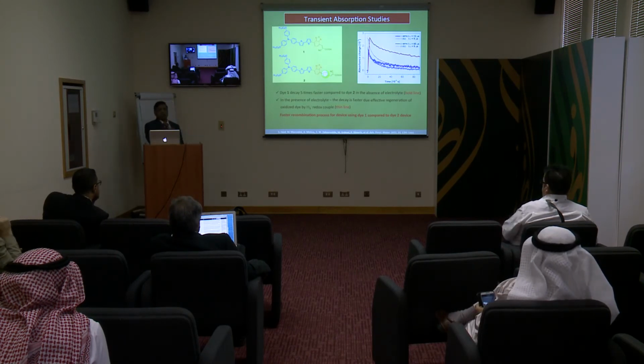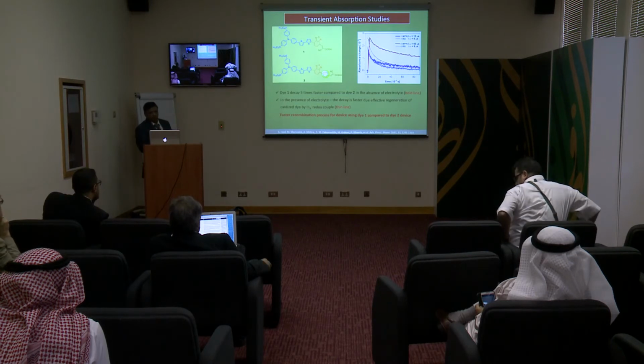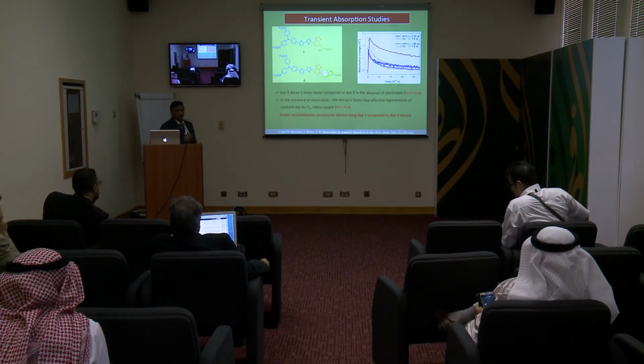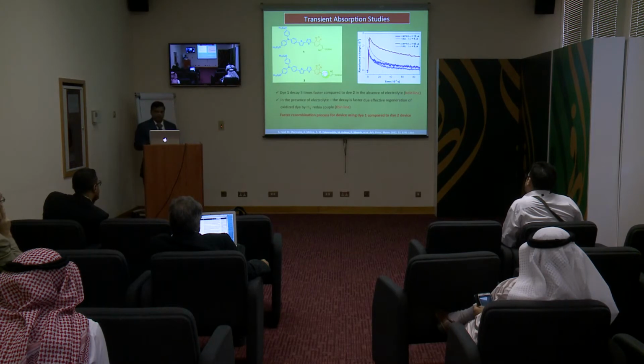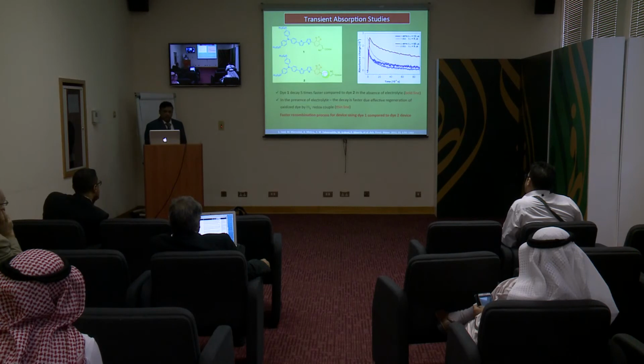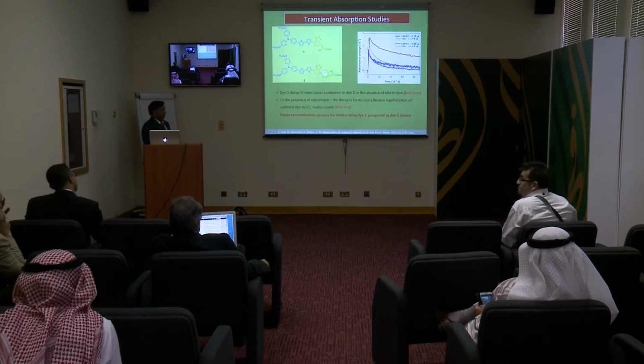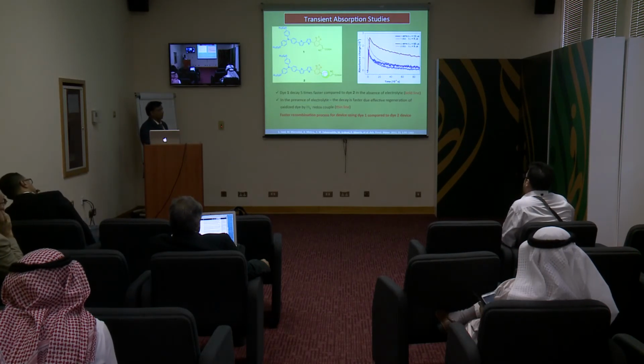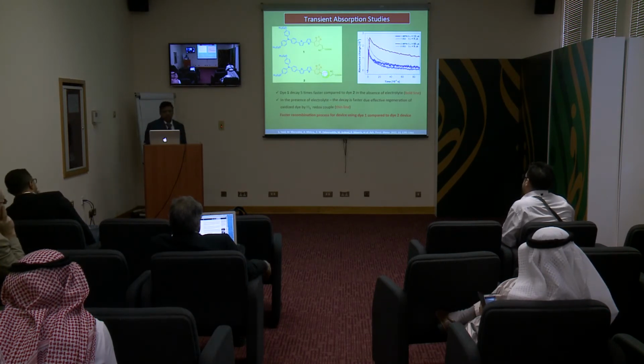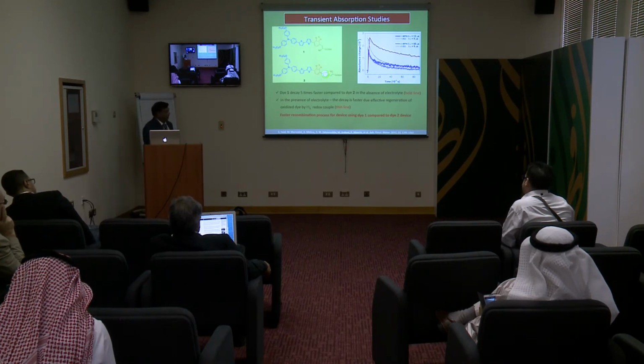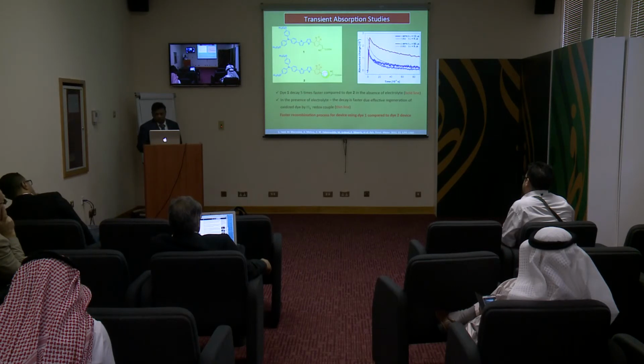So that means as soon as it injects the electron, the positive charge on the dye is also disappearing. So it shows the faster kinetics of the recombination. There is a very small difference between with and without redox electrolyte; you hardly see a difference in these two blue curves. Whereas in the case of dye 2, there is a huge difference in the presence of redox electrolyte compared to the absence of redox electrolyte. So this confirms that having a phenyl is an advantage next to the benzothiazole, except where it is close to the anchoring group.